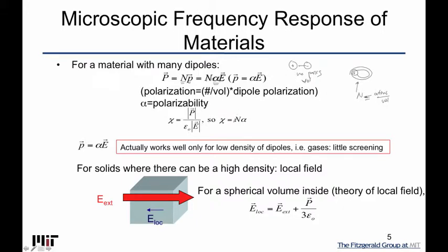Okay. So this is ultimately how you get in a measurement to the volume, because you measure something that is P, but you know the density of things in there, which brings out the polarizability. The electric field tells you how much is being distorted, and you get a sense of how big the thing is. There are some details here: the assumption that P equals alpha E is actually only good if you have very isolated ions. So when you have a very high density, like in an ionic material, the other ions shield it, but that can be corrected for, essentially screening.